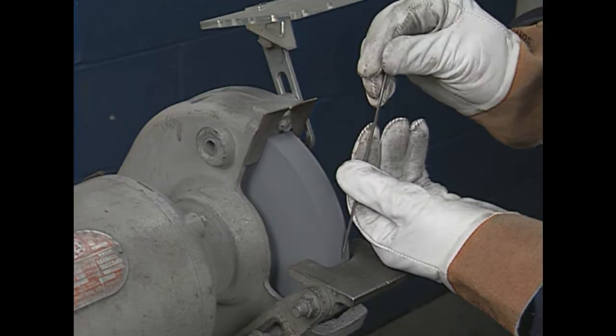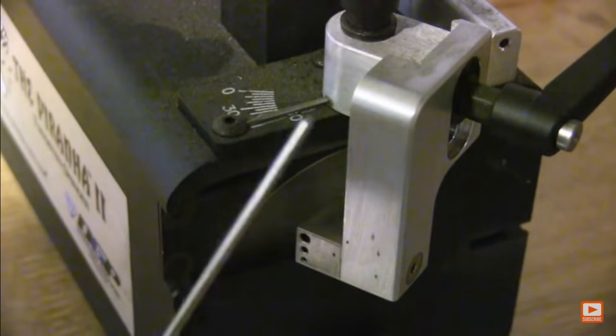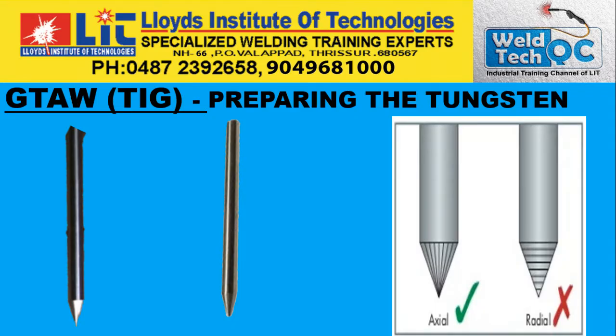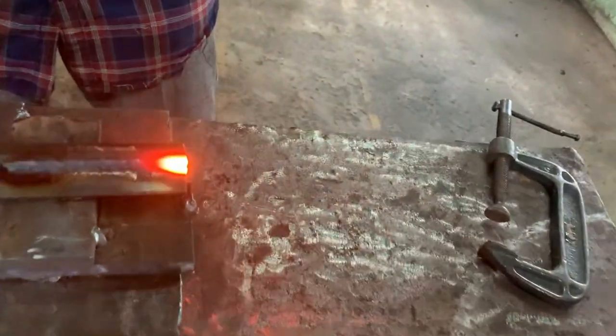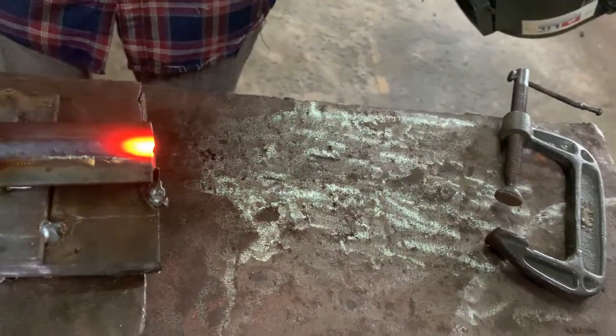A taper of no more than 2.5 times the electrode diameter creates a focused arc capable of producing deep, thin beads and a narrow heat affected zone. If it is more than 2.5 times, the arc may fan out, which will cause less penetration and a wide heat affected zone.